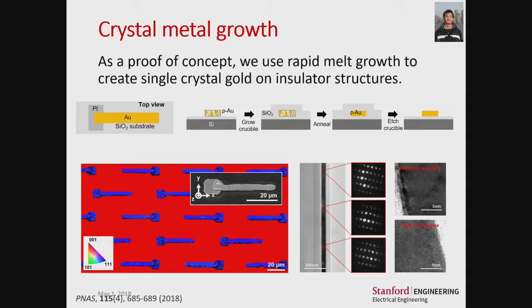Here we can see in this EBSD image that the yields can be very high. These are all single crystals of gold. And furthermore, interestingly, they all have 1-1-1 orientation out of the plane of the silicon wafer. And that is actually due to the fact that the fiber texture of the platinum seed is 1-1-1, even